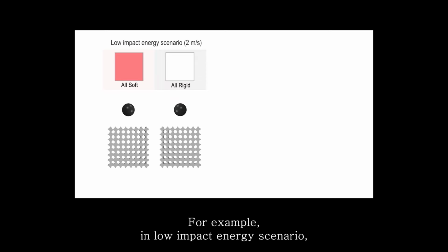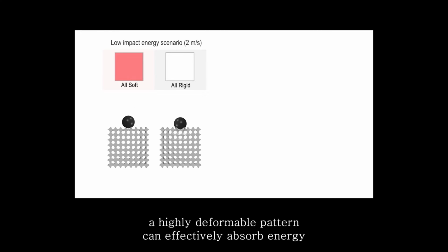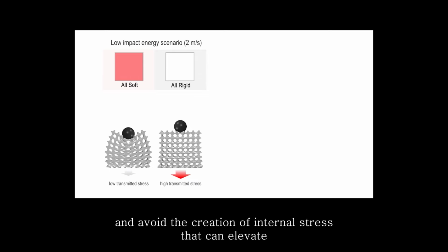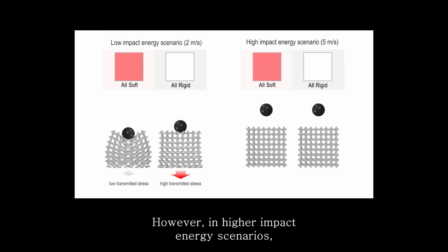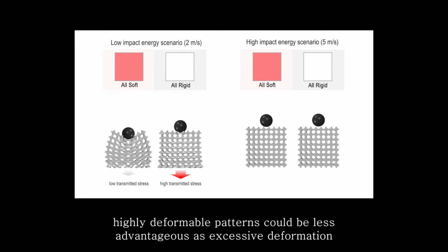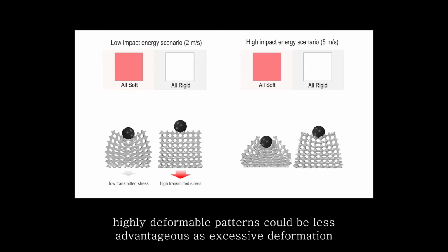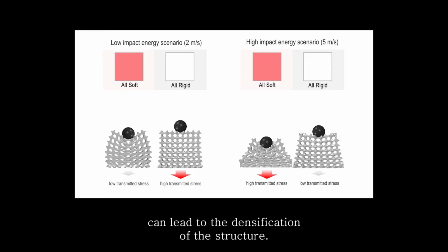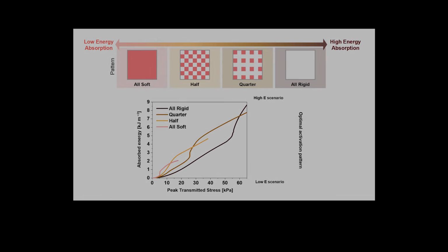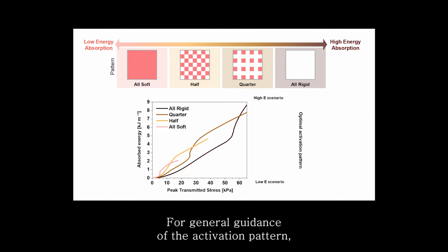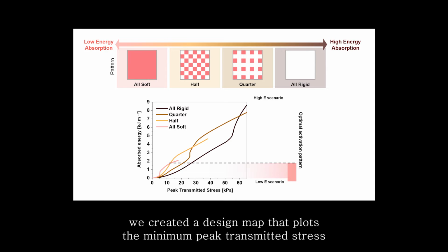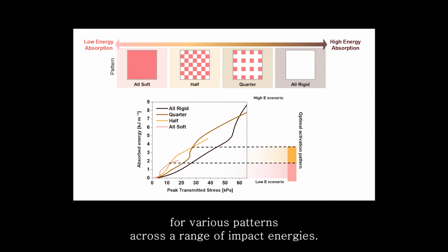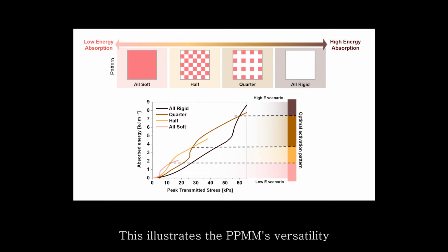For example, in a low-impact energy scenario, a highly deformable pattern can effectively absorb energy and avoid the creation of internal stress that can elevate the transmitted stress. However, in higher impact energy scenarios, highly deformable patterns could be less advantageous as excessive deformation can lead to the densification of the structure. For general guidance of the activation pattern, we created a design map that plots the minimum peak transmitted stress for various patterns across a range of impact energies. This illustrates the PPMM's versatility in adapting to different conditions.